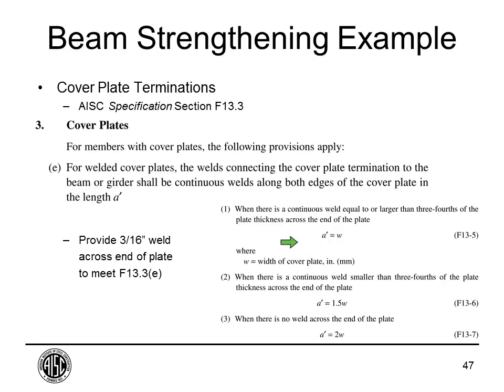So in our case, we have a 5-inch wide plate. If we provide a weld at the end of the plate, then the 6 inch weld that we just designed is adequate. If we didn't provide a weld across the end of the plate, then the termination welds would need to be a length of 2W or 10 inches. So in order to minimize the total amount of required welding, we'll add that weld across the end of the plate to meet this requirement.